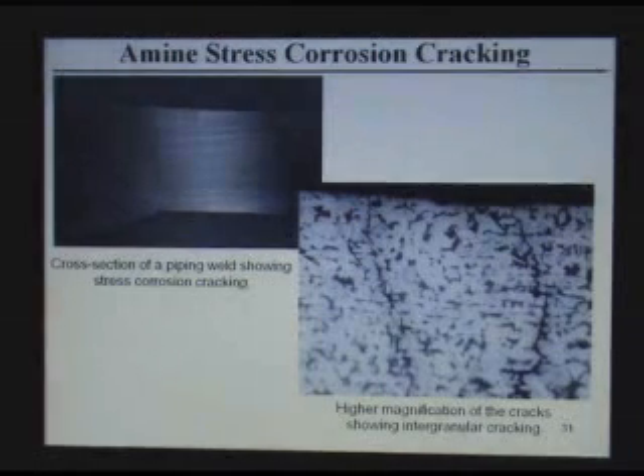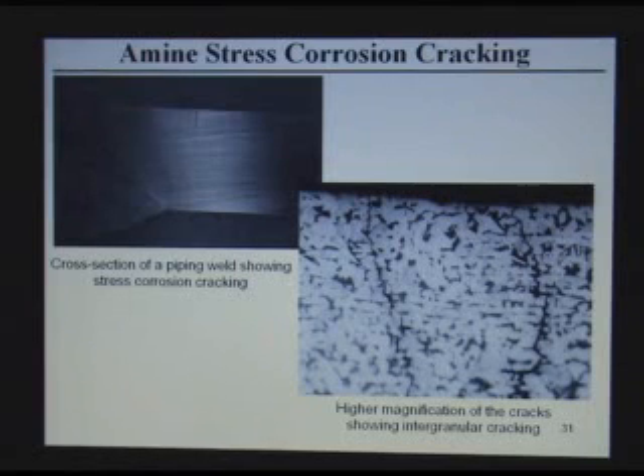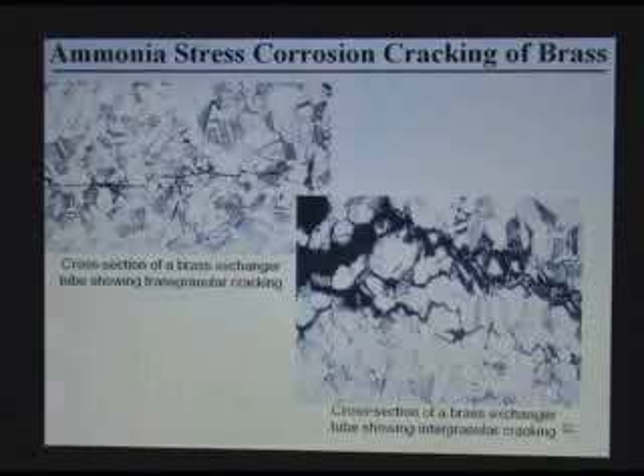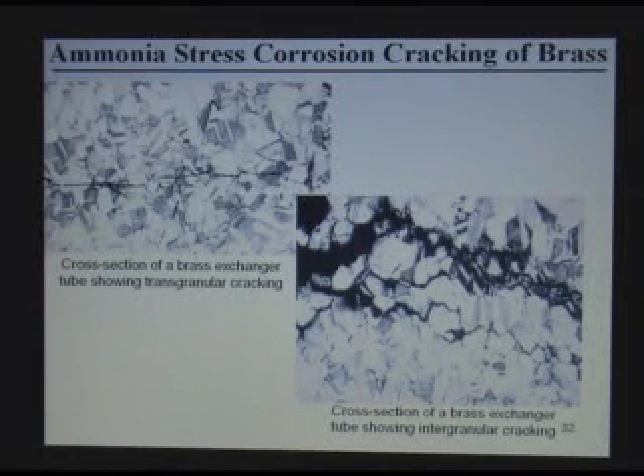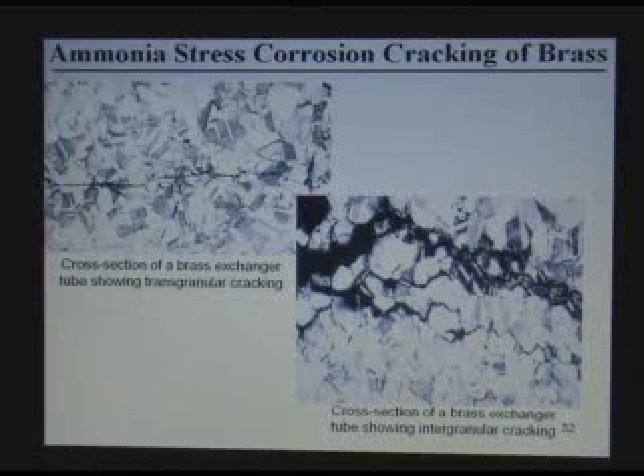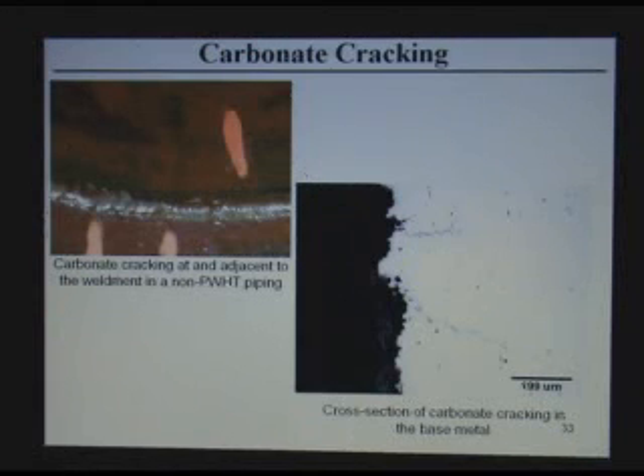Some examples: this is a crack next to a weld, and it is predominantly intergranular. If you have this structure, you have the intergranular crack. This is an ammonia crack in a copper alloy. You see it is almost intergranular, sometimes it is transgranular. Carbonate cracking, again, looks like intergranular type cracking.